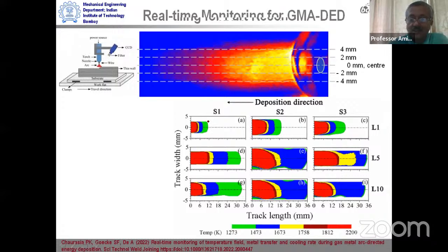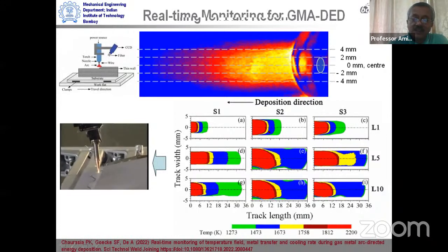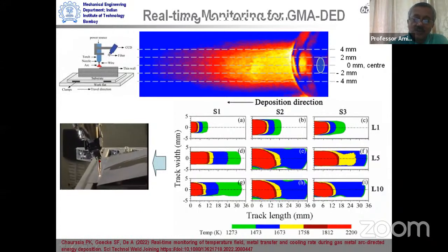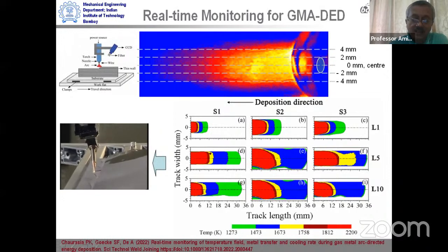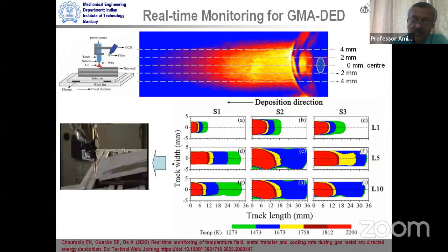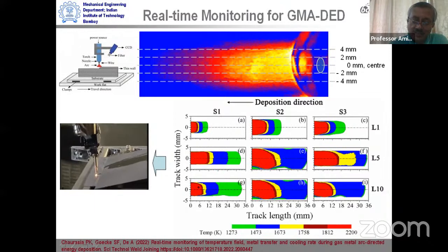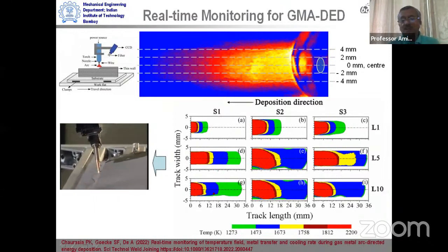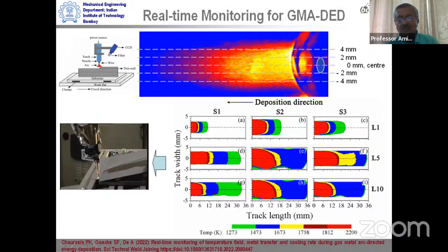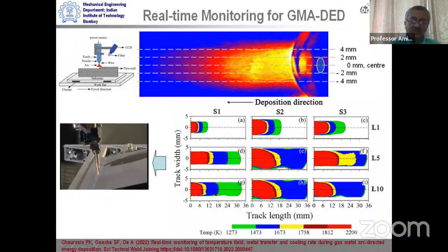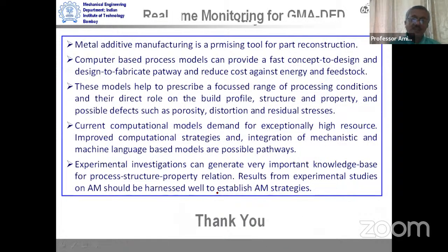And if you see, if it is a fast freezing fluid, it will be more symmetric compared to a higher heat input condition. So this tells us that it is possible to do a similar kind of deposition with a monitoring strategy with a very uniform shape, which will eventually provide us much more dimensional consistency during building of the process. Okay. So with this, I would like to stop with a few points as summary.